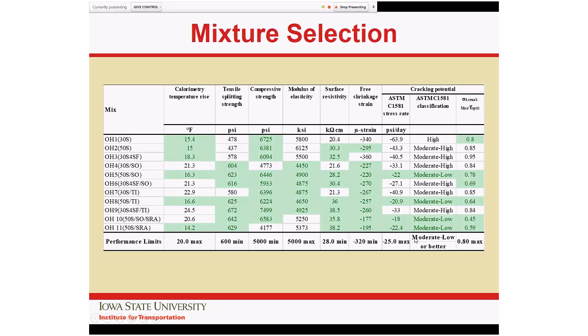And then from the ring shrinkage test, there are two parameters that we looked at: the rate of stress development and a parameter that you can extract out of the data, the risk of cracking. And so all of the cells with a blue shading are cells that seem to do better. Now, again, 4,000 psi is probably more than you need. In fact, 5,000 is probably way more than you need. But I was trying to filter out the systems that did better.